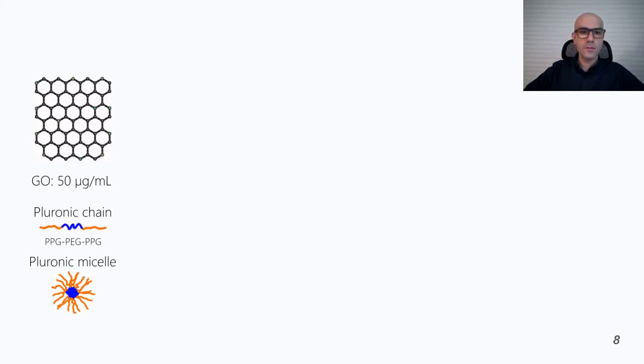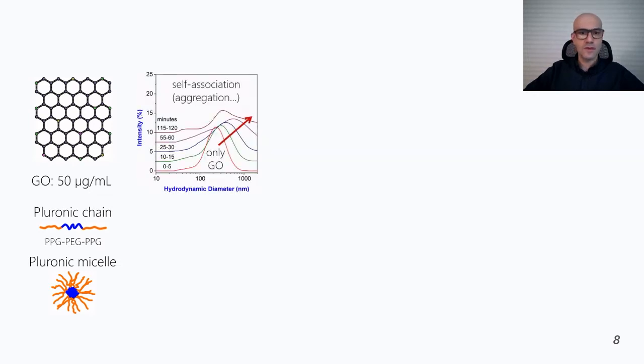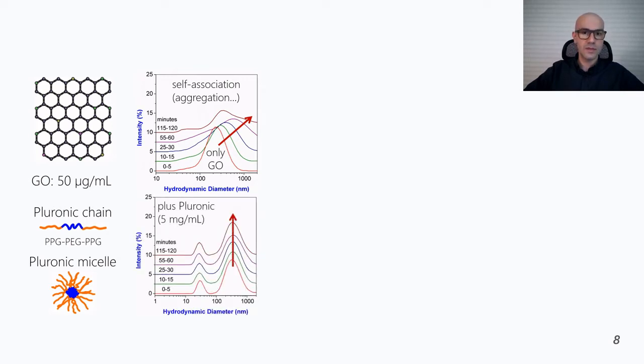Then, to increase the salt stability of graphene oxide, we combined it with a well-known polymeric stabilizer, a three-block copolymer of polyethylene oxide and polypropylene oxide, better known as pluronics. When there is no stabilizer, graphene oxide aggregates in time in the presence of cations, but in contrast, pluronic stabilized graphene oxide shows much higher colloidal stability when exposed to salt. As you see here, particle size distribution remains unchanged in time.